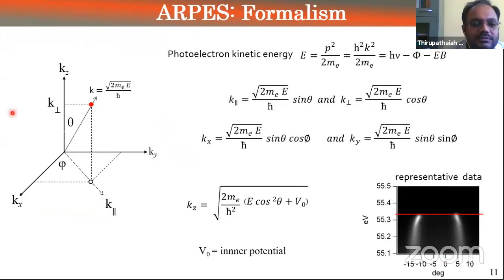So here I am schematically showing the momentum space in Kx, Ky, and Kz. If you think of Kz as the sample surface normal, and the photoelectron moving towards your detector, then you can project that onto the Kx, Ky plane, where you can resolve your momentum vector into Kz, Kx, and Ky. And here, just by knowing the takeoff angle, you can convert this kinetic energy formula into in-plane momentum and out-of-plane momentum.